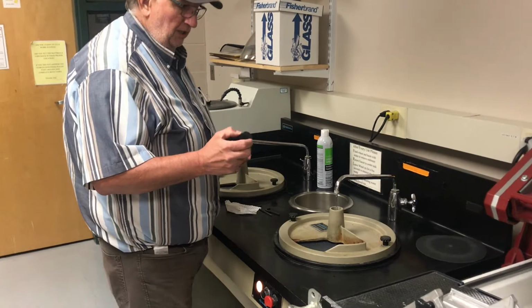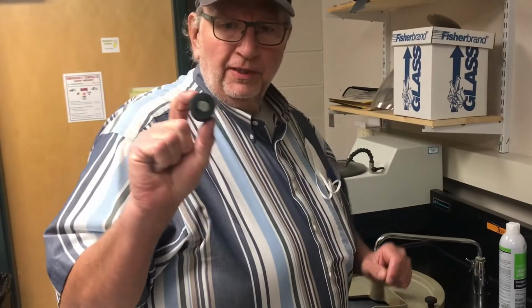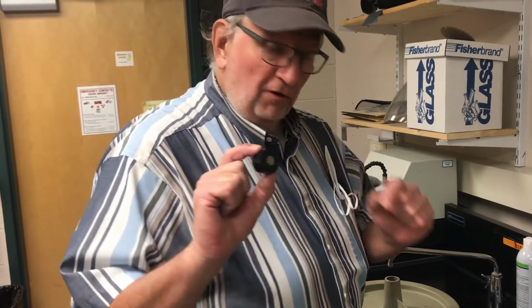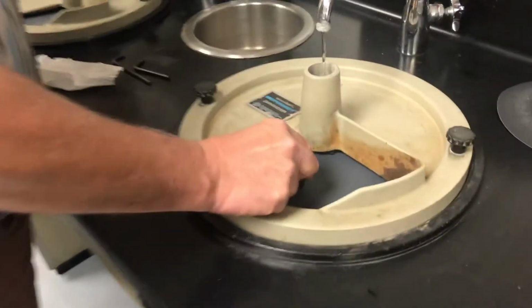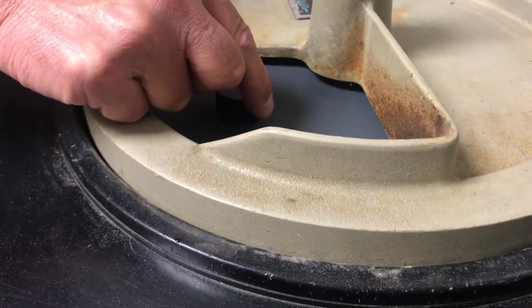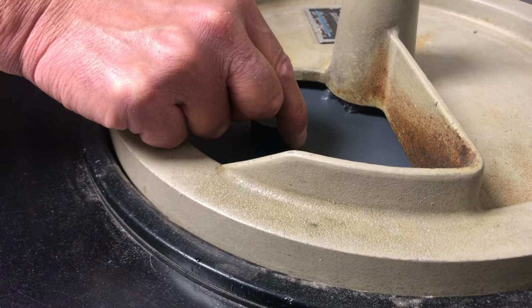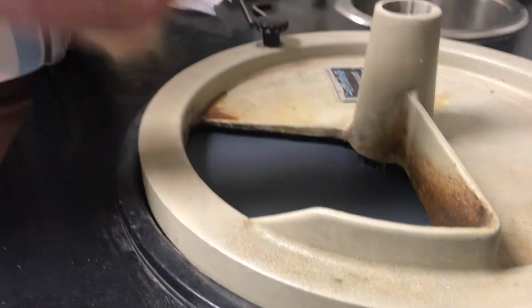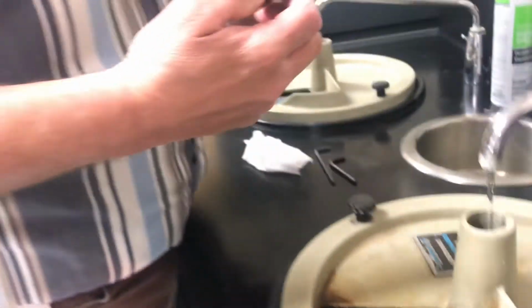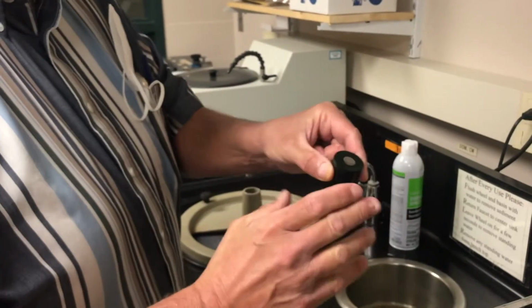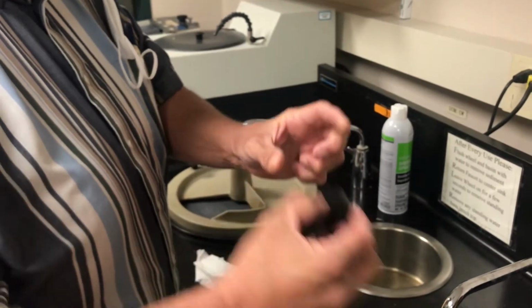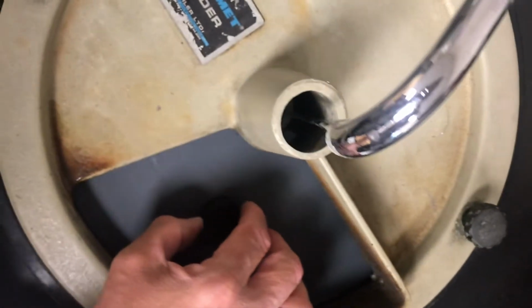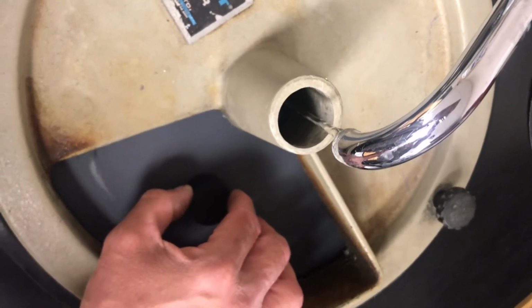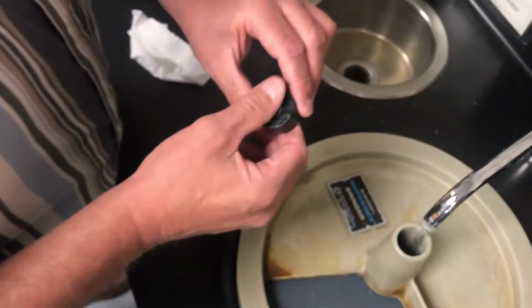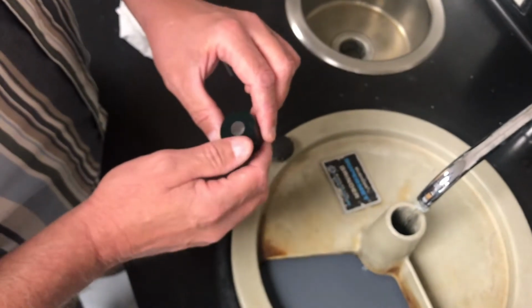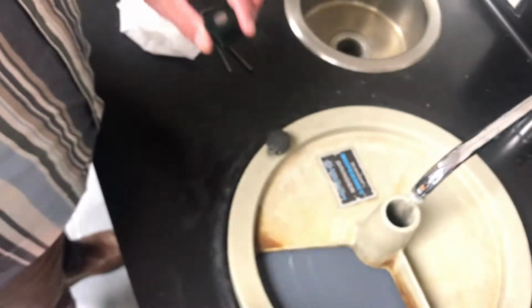But what you're going to do is start a rough polish. Take your sample, the side of interest first, down obviously. Try to hold the sample perfectly vertical, just a small amount of pressure, not a lot. Let the paper do the work. If you're not careful, you will end up with multiple facets on your sample, and that's hard to get back from. So just try to press evenly and try to get a rough polish to cover the entire sample. It should be nice and shiny, and that's all you're trying to achieve with this step.